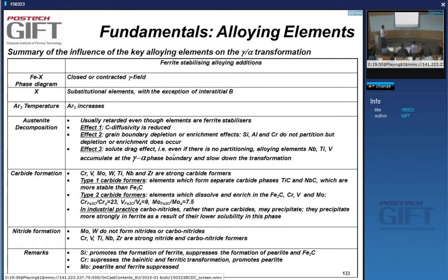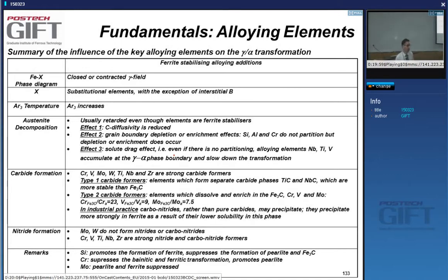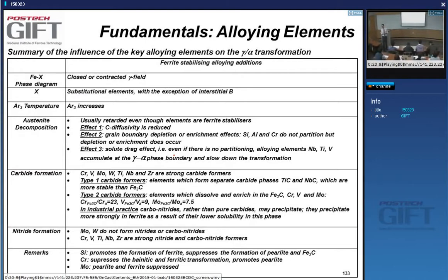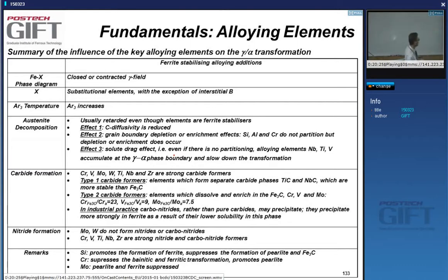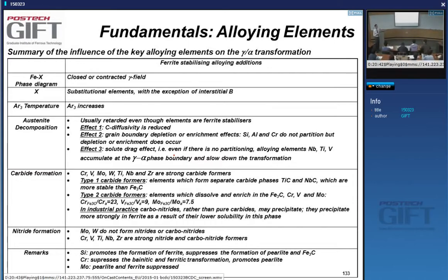In industrial practice it's more complicated — very often the carbides are not pure carbides but carbonitrides, a mixture where carbon and nitrogen form compounds with elements like chromium. These carbides and carbonitrides precipitate strongly in ferrite, particularly during the transformation from austenite to ferrite, because their solubility in ferrite is much lower than in austenite. They precipitate and form many small precipitates.